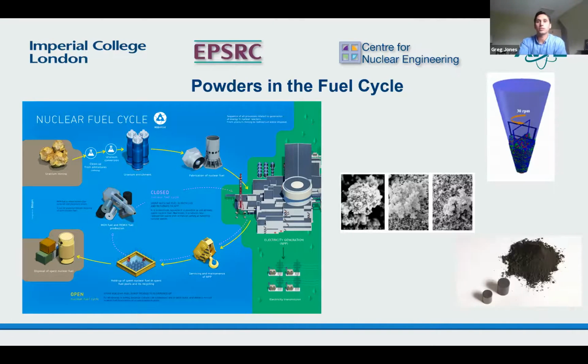In the image on the bottom, you can see uranium dioxide as a powder, which is then crushed into pellet form in these fabrication and processing facilities. The powder is usually held in these cylindrical vessels. Double contingency measures are usually in place, which entail specifying subcritical packaging limits, whereby if the packaging were to get fully immersed in water, a criticality excursion wouldn't be reached. The other contingency measure is a moderating insert, which is usually that.